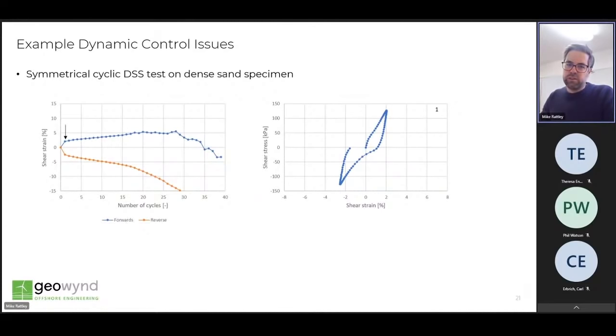The first cycle produces a nice clear hysteresis loop, and that might be expected for the sort of medium dense sand being tested. The peak strains here are within a couple of percent, but on the third cycle, the strains have increased slightly, but the test response is still stable and the strains are reasonably well balanced in the forward and reverse directions. However, by cycle seven, we start to see the onset of significant concavity in the stress-strain response, which is also typical of dense sands and occurs due to changes in the dilational response of the soil during unloading and reloading.